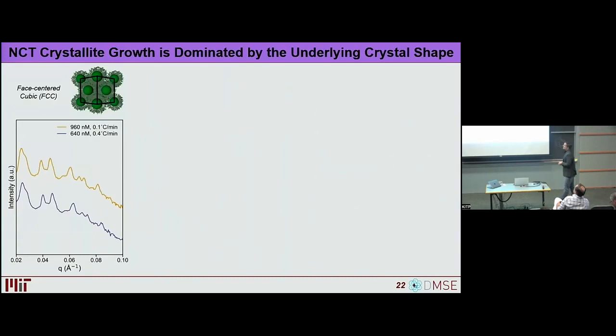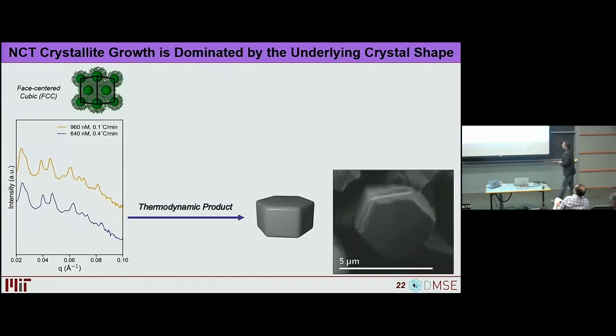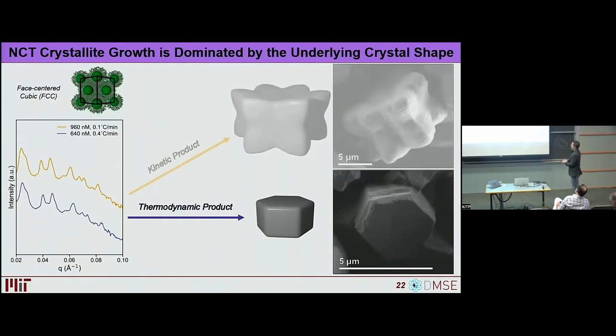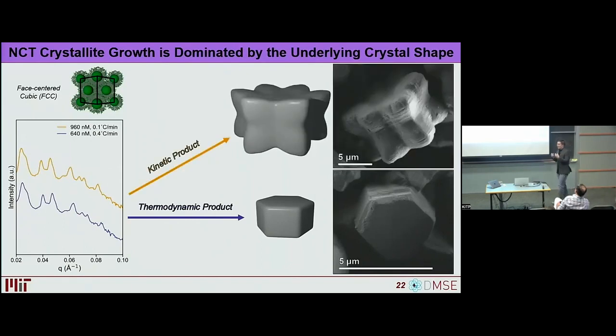We can test this hypothesis by going back to those FCC type structures. So if we assemble it under two conditions, one that should favor a rapid growth of smaller crystallites and one that favors much larger crystallite growth, what we can see is that in the case where we favor the thermodynamic product that's a little bit smaller, we get, again, these sort of hexagonal type structures. What we predict, based on what I just explained, is that we should see growth at these 12 corners at the top and the bottom of the crystallite, and that's exactly what we see. So it's not anything at all about the crystallographic symmetry that's dominating this growth. Otherwise, we would not see this 12 or 6-fold symmetry coming from an FCC lattice. Instead, it's the underlying crystal shape.